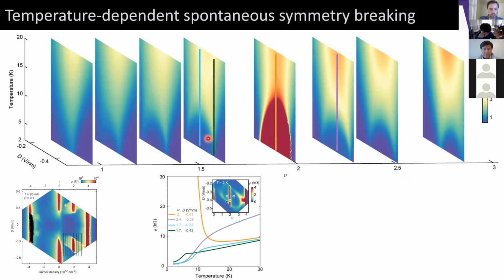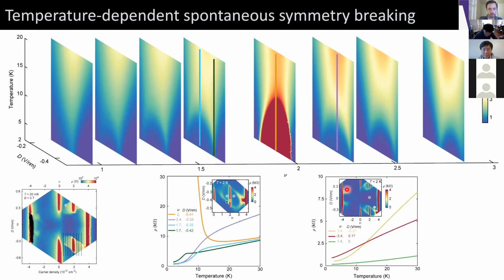If I take cuts at filling factors that are slightly detuned from half filling, the system is metallic, but it's a very odd metal. At high temperature, it has this canonical linear in T behavior that's standard of multilayer graphene. But then below some temperature, roughly around the onset of insulating behavior, it has this abrupt downturn in resistivity and saturates to some lower value. And the onset temperature of this abrupt downturn depends on where I take this cut. If I take it precisely at the center of this arch, then the temperature is high. If I take it at the edge of this arch, which means the edge of the halo, then the temperature is low. And again, this contrasts what we see outside of these halo regions, where we don't think the system is strongly correlated. In that case, the temperature dependence looks a lot more conventional of graphene, where we have linear in T decrease of the device resistivity as we cool, and then at low temperature it saturates, owing to the freezing out of phonon scattering.